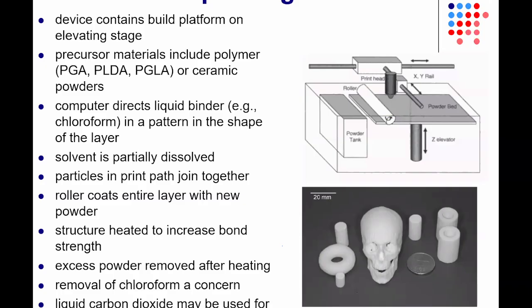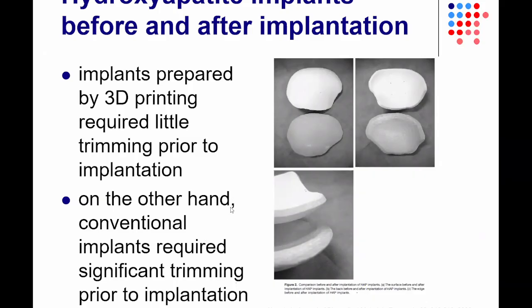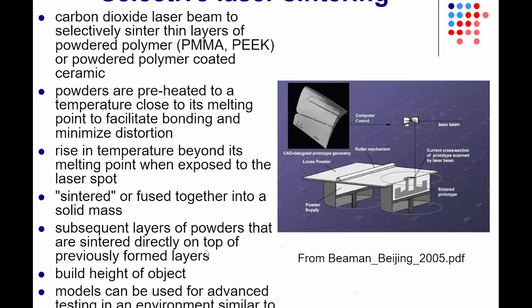One of the things that you also need to worry about is when you're binding together materials, the binding agent can be a concern. If you're binding together, in this case, a polymer powder with chloroform, the chloroform binding agent can be a concern. You can use liquid carbon dioxide to remove that solvent. Here you can see hydroxyapatite implants before and after implantation created by powder bed fusion. And you can see the advantage of this is that you can print a structure that doesn't require very much trimming, and you can essentially use the part coming off of the printer directly in implantation studies.